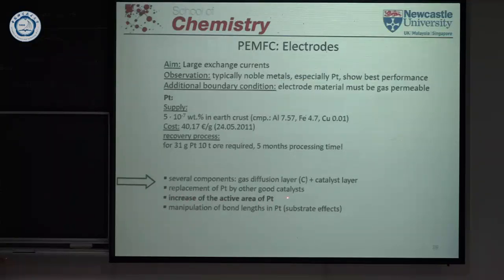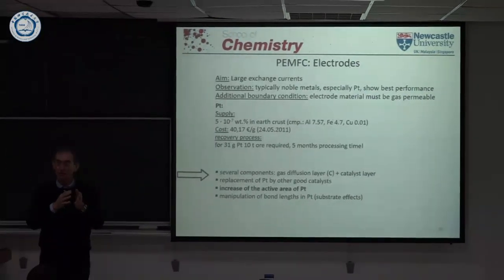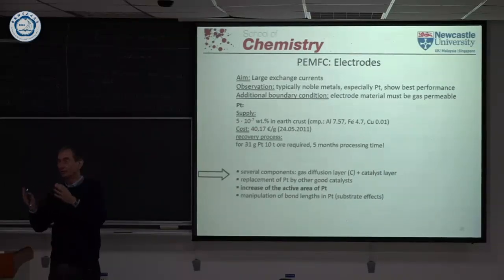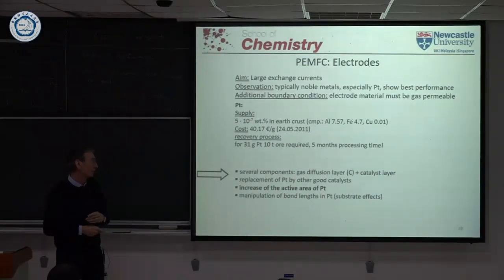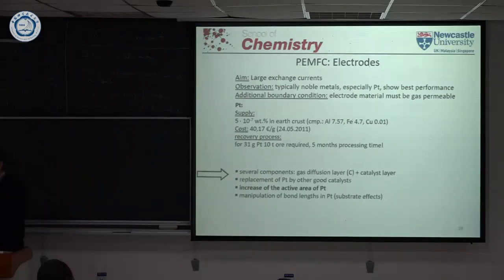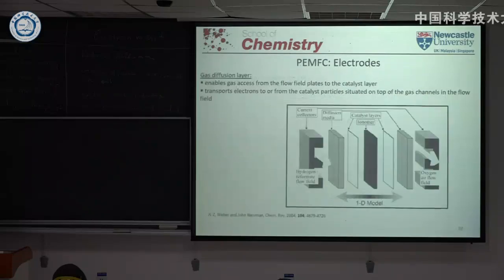This is a very important aspect to follow, and that has entered this business. But then there are some very subtle effects, I would say. Taking platinum and putting it on some other metals introduces so-called substrate effects. That means that the bond lengths change, and that may have some positive effect on the electrocatalytic behavior, but may also have an opposing effect. So I have to find out what this combination means. There are a number of things I need to understand before I can really make an ideal cell.